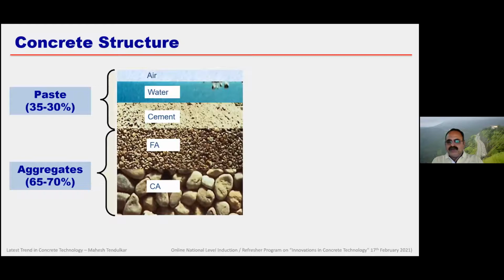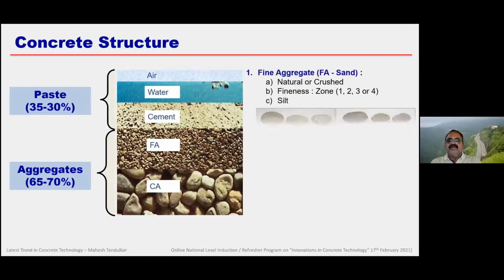If you closely monitor the failure of a high grade concrete block or cube, you will find sometimes the failure is through the aggregate. It is not a bond failure, it is an aggregate failure. So we have to select the proper aggregate, particularly in high grade concrete, say 50, 60 onwards. Selection of aggregate is very important. And not only selection, I insist that one must visit the crusher and understand the manufacturing process and confirm that the quality of aggregate produced there is up to our required parameters.